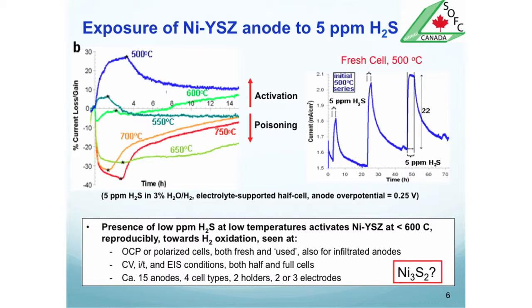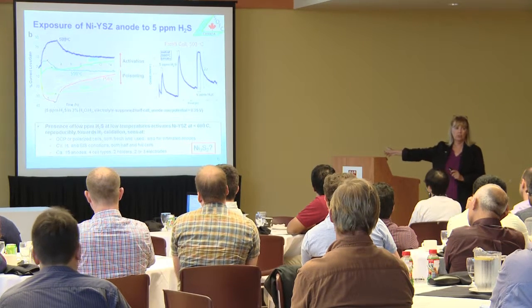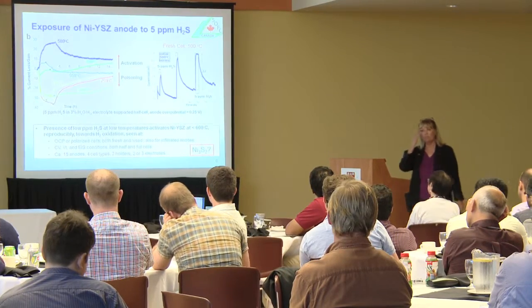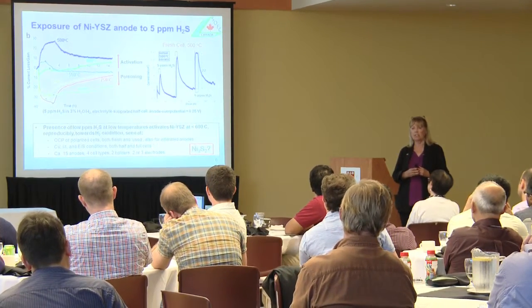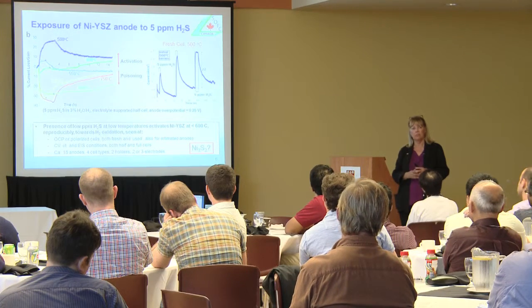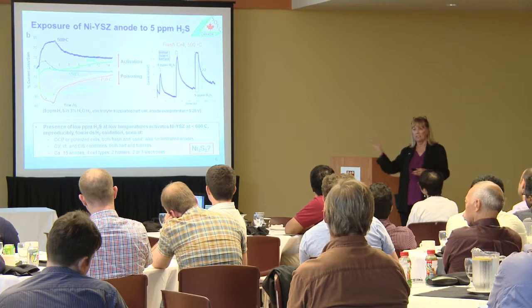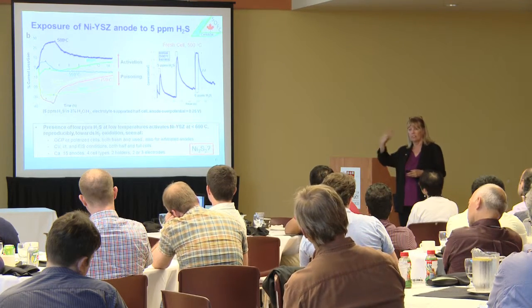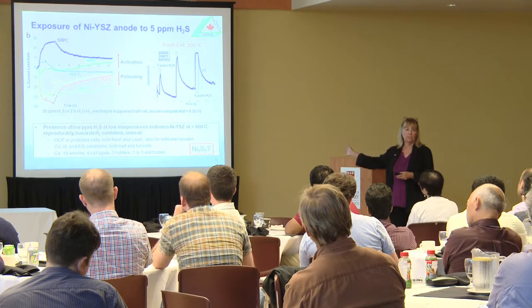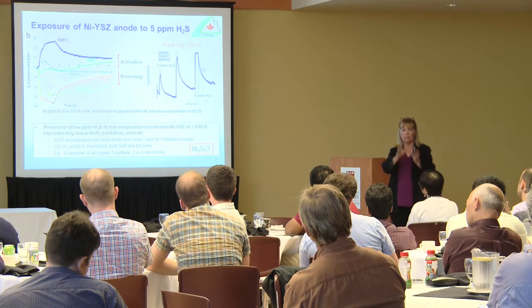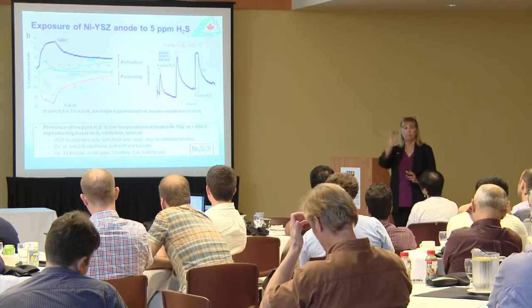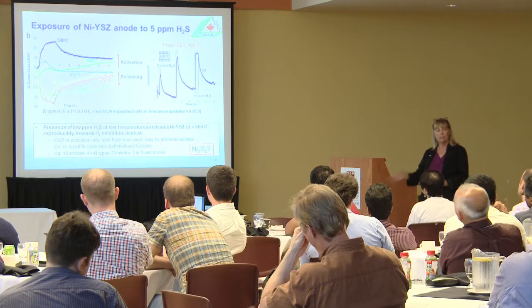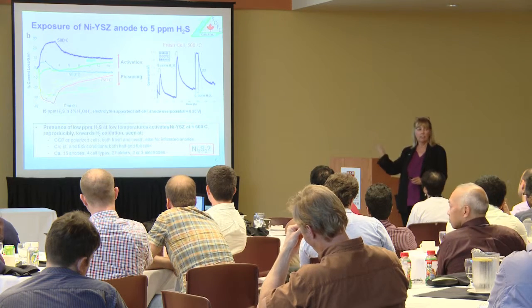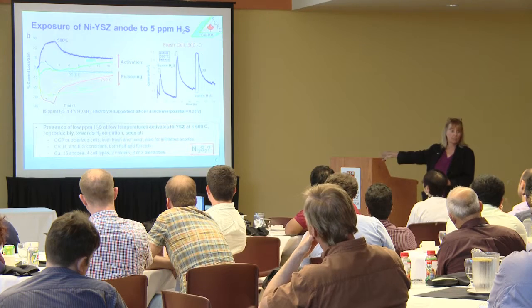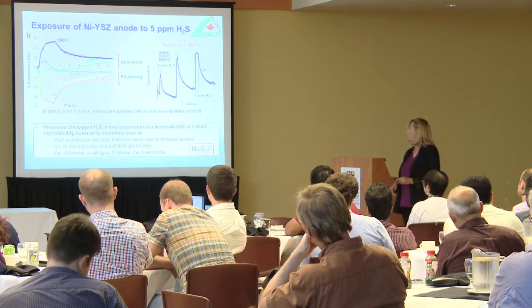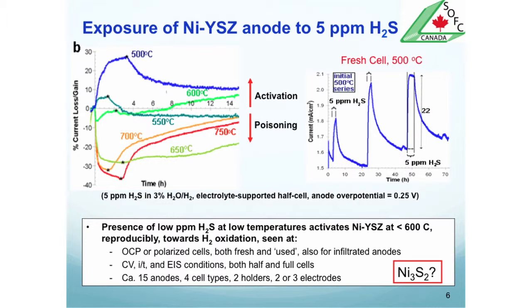So what we did is we started to think about what could this be, and I put here Ni3S2 in the right-hand corner, bottom. We started to look at the literature on this, and we found for sure that Javier's group in Ottawa has seen that when you completely convert nickel to nickel sulfide under other conditions, they too see catalysis of hydrogen oxidation. They go from nickel YSZ to Ni3S2 YSZ, and the current gets better for hydrogen oxidation. So there's that. On the other hand, Kunal just pointed out that our conditions should not really produce this stuff. There's not enough sulfur, and the temperature's not high enough, or low enough, either one. So really we shouldn't have that.